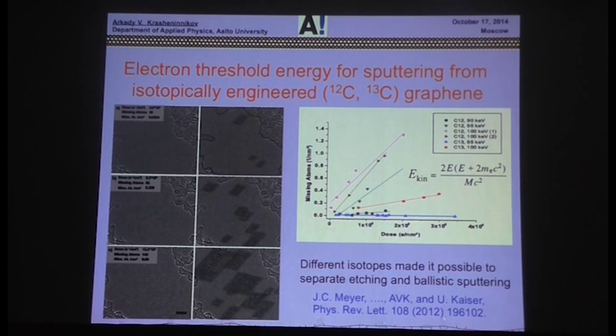So this means that when an electron kicks the atom, in normal graphene, if you're very close to the threshold, meaning the minimum energy of the electrons at which they start knocking out atoms, in graphene-12 you will knock out atoms, in graphene-13 not. And that is exactly what you see in the experiments, if you plot the number of missing atoms as a function of radiation dose or simply time. In graphene-13, nothing happens. In graphene-12, it loses atoms pretty quickly. Unfortunately, the projector is not very good here. You cannot see individual atoms. It's a bit dark, but still, I think you got the idea.